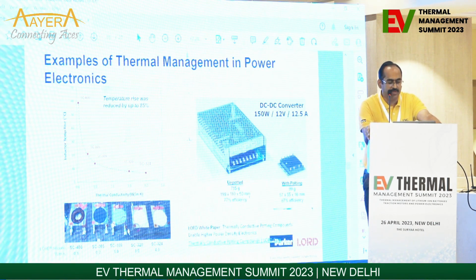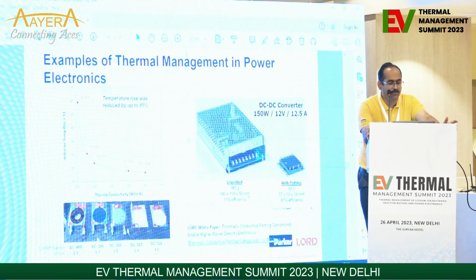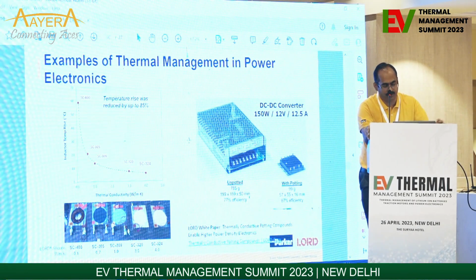And at left, basically, we have shown a graph with our potting material with thermal conductivity ranging from 0.1 to 4 watt per meter Kelvin, and how the performance is affected and how temperature rise is reduced by up to almost 85%.